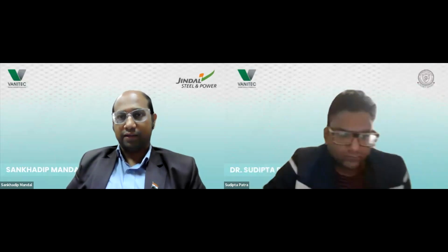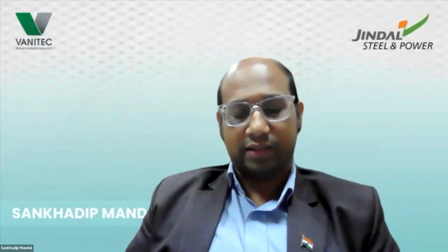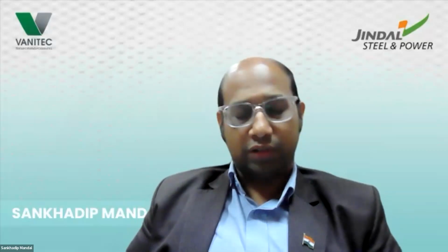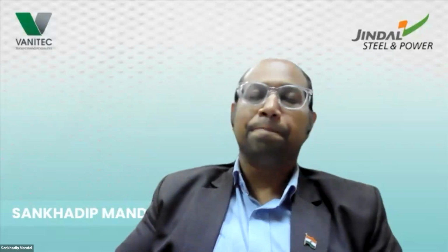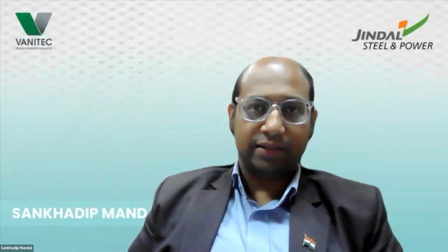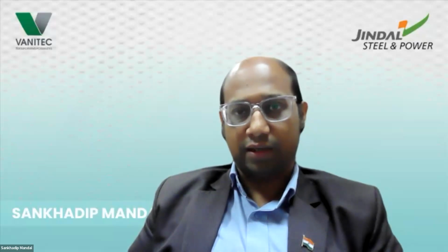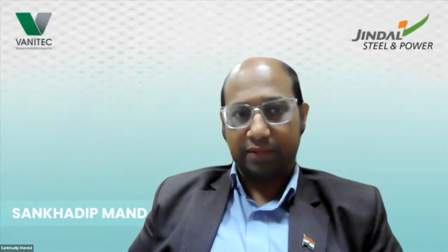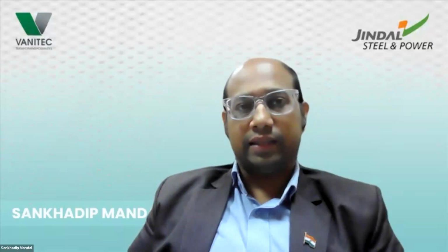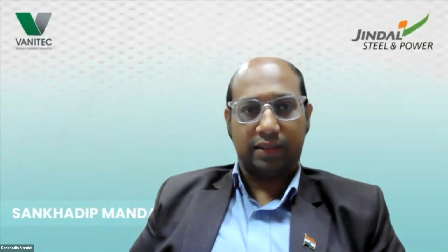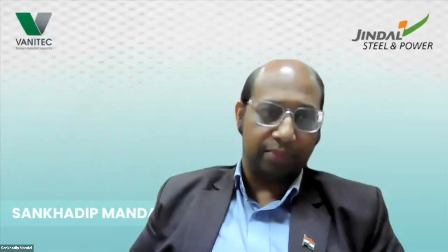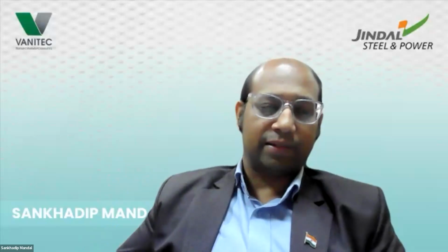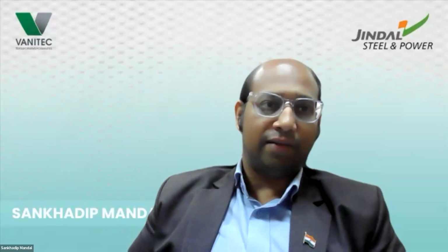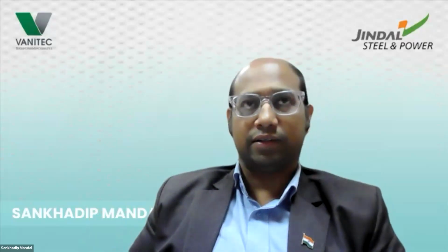So when it solidifies from the liquid stage in the continuous caster, there will be two situations in the equilibrium scenarios. There will be combinations of different nitrides, because of the affinities with nitrogen, with the aluminum, as well as the others; titanium has more affinity also. So it will form the high temperature precipitates. Titanium gives the highest temperature precipitates, then aluminum, and then vanadium will come into the picture. Niobium will come into the picture, and gradually it will come down as the solidification process happens in the continuous caster.